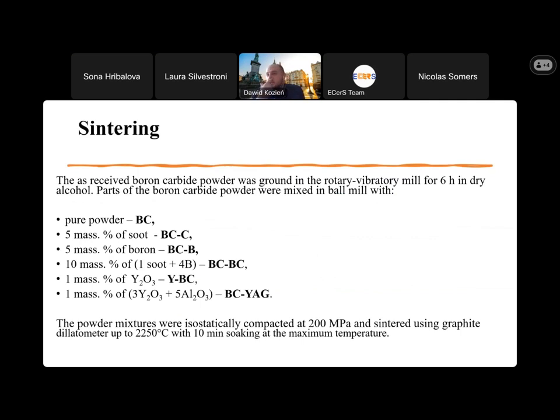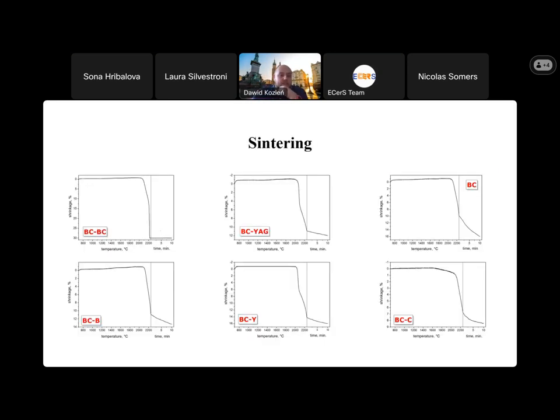And we start to assume the situation of what we do when we add something to get better sintering, only boron carbide. So we assume that if we have non-reactive boron carbide that has more boron or carbon in the structure, we have better sintering. So we add carbon, boron, we even add boron, so that we have obtained more boron carbide, yttrium oxide, and aluminium oxide with yttrium oxide, because we want to obtain garnet. And after that, we sinter.